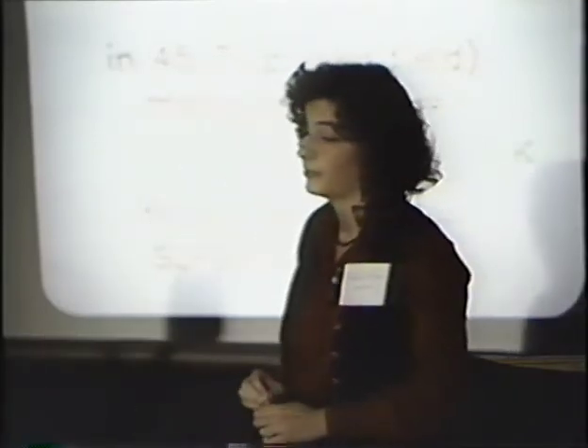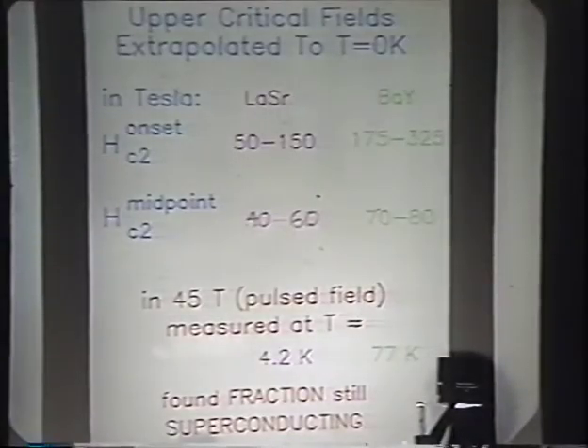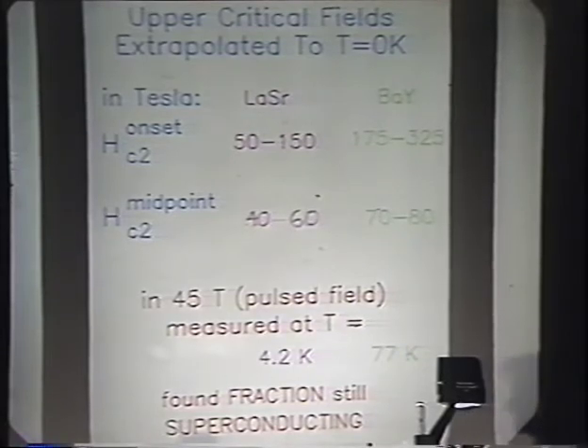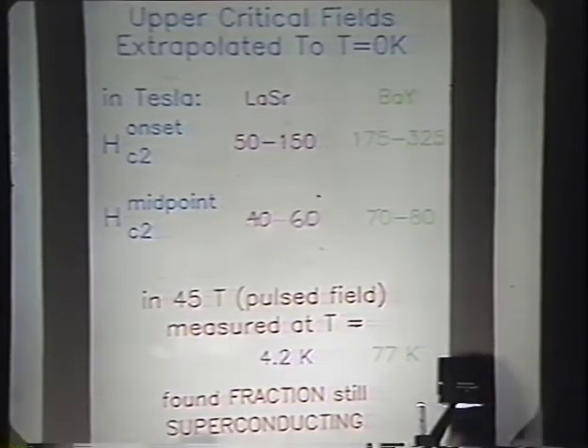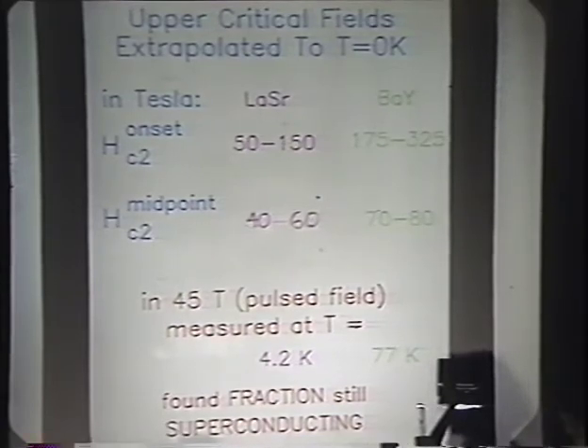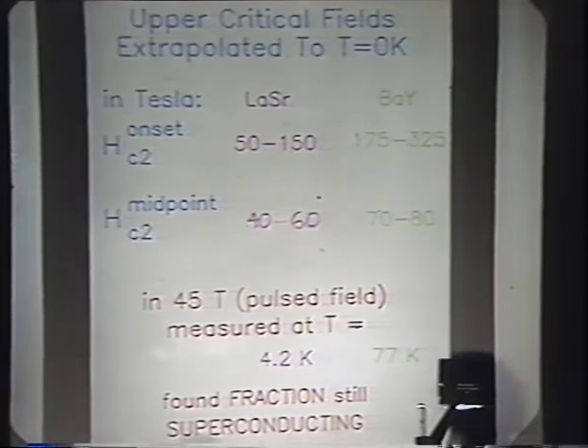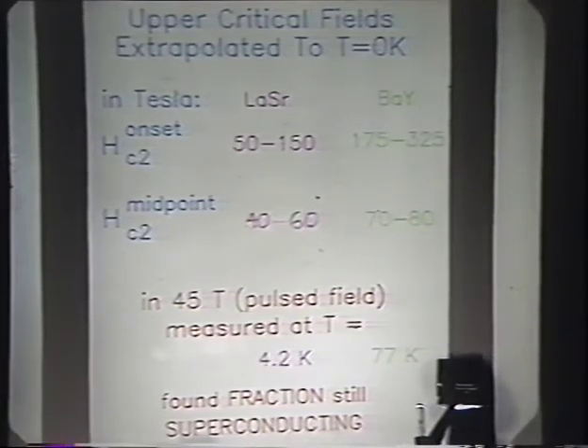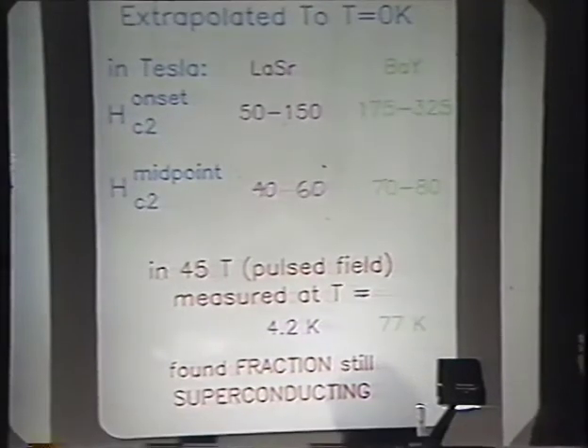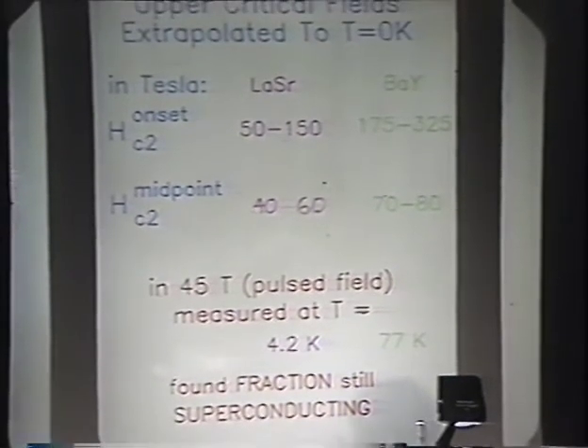I've summarized the Hc2 values in the following table, extrapolated down to zero temperature. The numbers are printed in Tesla. Note the surprising result: the barium yttrium compound, agreeing with the earlier Bell Labs presentation, extrapolates at zero temperature to between 175 and 325 Tesla, which is one of the highest Hc2 values seen to date for a high Tc material. I'd also like to point out that the pulsed field data was done at 45 Tesla. The lanthanum strontium material was measured at 4.2 K. The barium yttrium material was measured at 77 K. And in both cases, a fraction of the material is still superconducting at 45 Tesla.